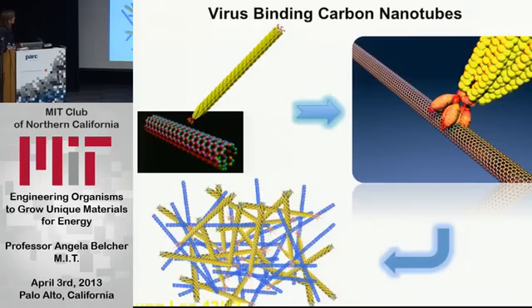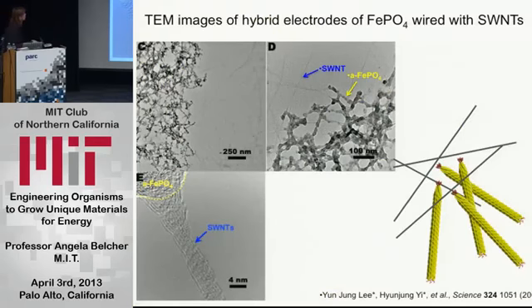And so here's what they did. They were able to use this minor coat protein to grab onto the CNTs. And then looking at the transmission electron microscope image here, the darker part is the iron phosphate, and hopefully you can see these carbon nanotubes that are basically coming off here.